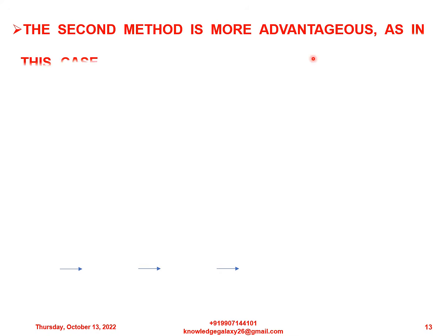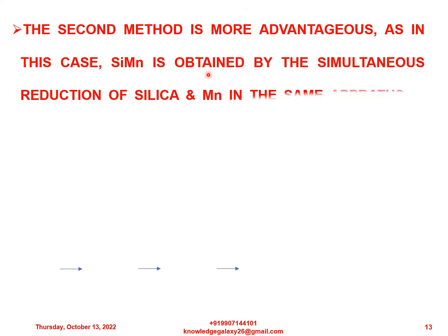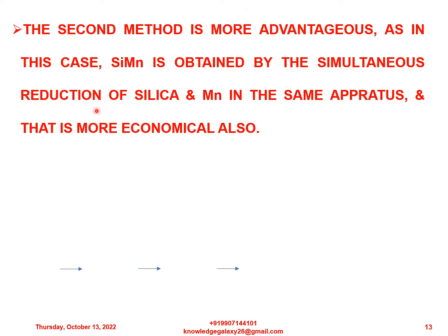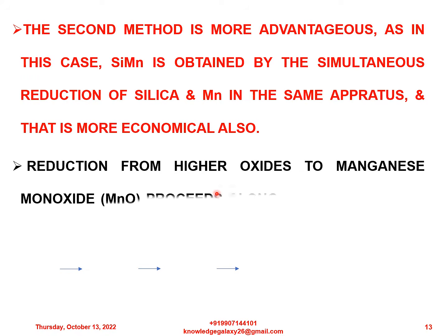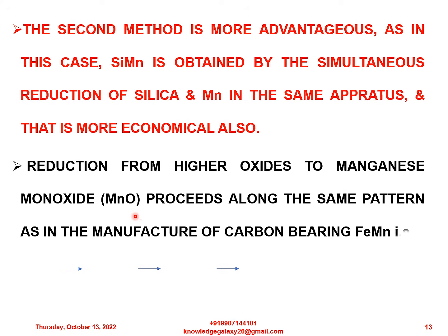The second method is more advantageous, as in this case silicomanganese is obtained by the simultaneous reduction of silica and manganese in the same apparatus, and that is more economical also. Reduction from higher oxides to manganese monoxide, that is MnO, proceeds along the same pattern as in the manufacture of carbon bearing ferromanganese. These are the steps by which manganese higher oxides are converted into lower oxides: MnO2 transforms to Mn2O3, then to Mn3O4, and finally Mn3O4 transforms into MnO.